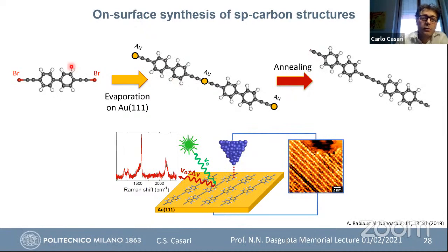So by collaborating with the group of Wei Xu in Shanghai, starting from this molecular precursor, if you evaporate this with bromine atoms on gold, you have the release of the bromine atoms, and gold is replacing bromine and forms this kind of metal organic structure. If you anneal the system, you can have the removal of gold and a homocoupling of the carbon atoms here, and have a very long sort of sp polymer.